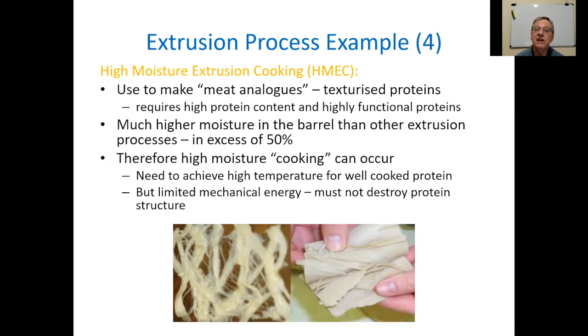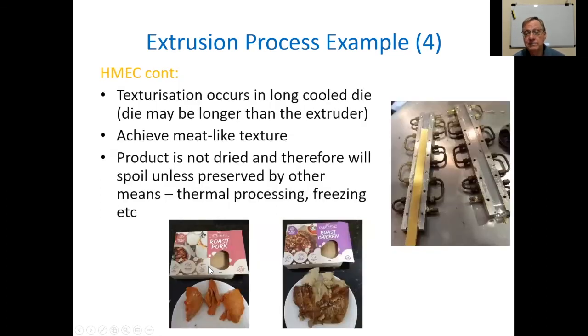We need to develop very high temperatures to cook the protein, unravel those protein molecules, but we don't want to destroy them, not too much mechanical energy, because we want to then line up those proteins and produce a fibrous type of structure. And we do that in the die, not in a small hole, but in a long, cool die. And in this case, as the melt passes through the die, it solidifies. The velocity profiles that are developed encourage those protein strands to line up and allow the cross-linking to occur between those fibres, and we get the meat-like texture.